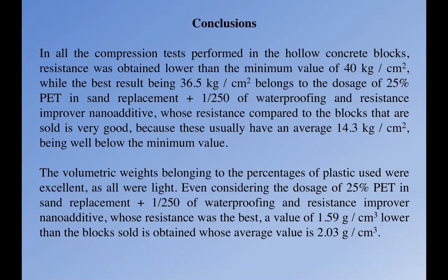conducted a study where we can see that all the compression tests performed on the hollow concrete blocks had resistance lower than the minimum value of 40 kilograms per square centimeter, while the best result, 36.5 kilograms per square centimeter, belongs to the dosage of 25% PET and a sand replacement of 1 to 250th of waterproofing and resistance improver nanoadditive, whose resistance compared to the blocks that are sold is very good, because these usually have an average of 14.3 kilograms per square centimeter, being well below the minimum value.